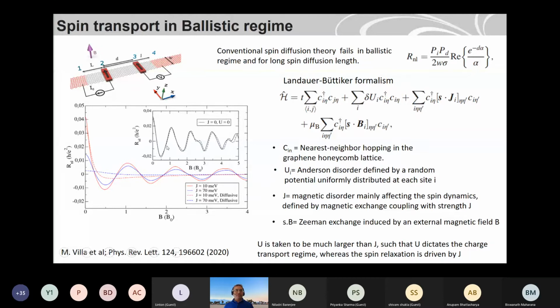So what you see is, in the Hanle experiments that I showed you, you just see one peak and then a dip, then it's gone. But if it is ballistic or quasi-ballistic, you should be able to see multiple oscillations. There are some new features coming because it's a high magnetic field, then Zeeman can also contribute. There may be other parameters which influence this. So you can also calculate that with different J parameters, which is actually this magnetic disorder. And that is quite useful to understand if we make such devices in future. And that's also quite challenging. I'll show you what the challenges are to get such ballistic spin transport.